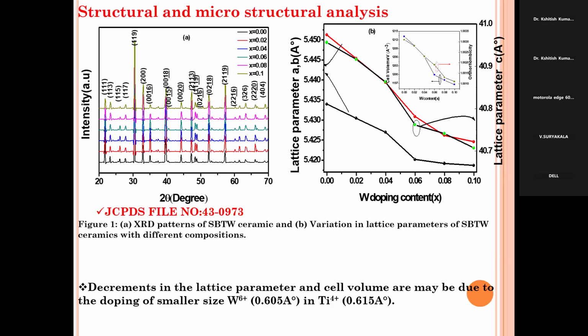The reason may be the smaller ionic radius of the tungsten compared to the titanium. The ionic radius I have mentioned here is 0.60 angstrom for tungsten and 0.61 angstrom for titanium. So we thought that maybe due to the smaller ionic radius of the tungsten, the lattice parameter gradually decreases. The next question is, if the lattice parameter gradually decreases, how does it affect the electrical properties of the material? What about the dielectric constant, and what about the piezoelectric constant?